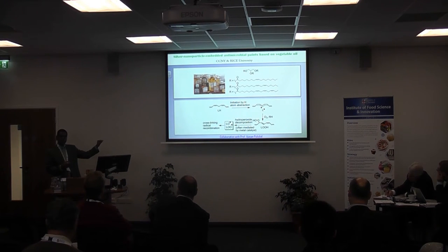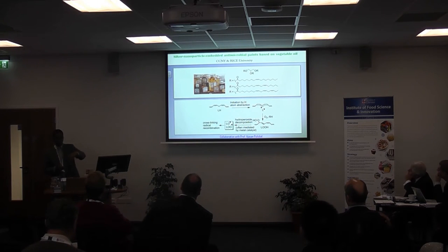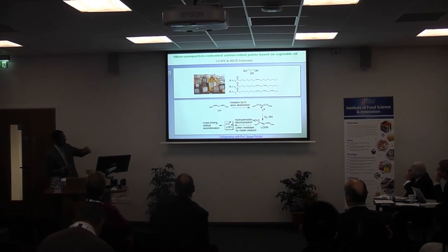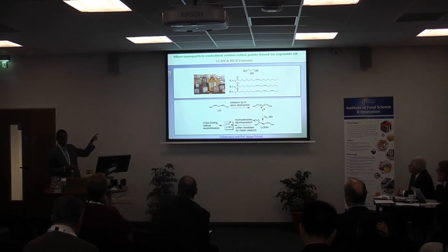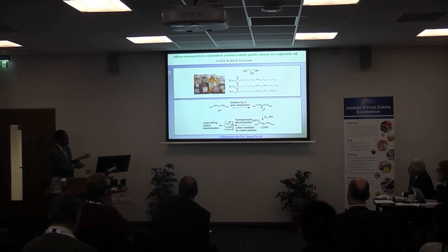These free radicals are nature's chemistry, we don't do anything. It happens whenever there is vegetable oil, because it abstracts oxygen. And these free radicals are known to reduce noble metals into zero-valent metals. If you start with gold Au3+ metal ions, you get Au0. If you start with Ag+, it will turn into Ag0. With platinum, you can convert it into platinum zero. That is known in the literature.